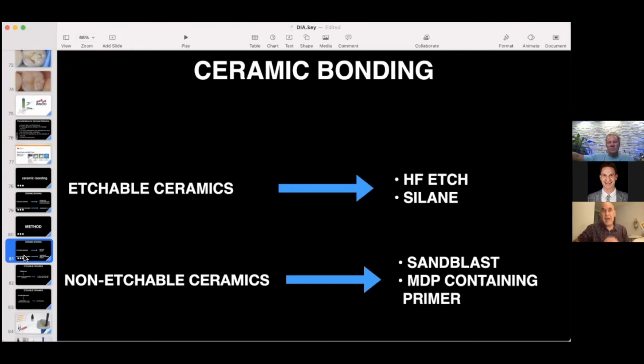So I have found that pure silane, regardless of the brand, whether it's 3M, Kerr, Dentsply, Ivoclar, or Bisco, works better from a bond strength perspective than these concoctions that include silane. Why is that? Because silane is very temperamental. Silane doesn't like to be in low pH environments, and that's what happens when you mix it with MDP. It becomes inactive over time. The bond strength is not as good. The literature has shown this. This is not me talking, this is the literature. So it is always better to use pure silane.